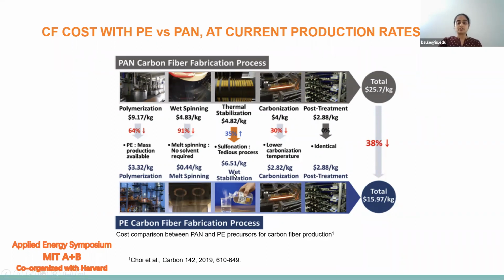Another major difference is that polyethylene is a thermoplastic, so it has a lower melting point of around 140 degrees C. Therefore, it requires some pre-treatment, that is thermochemical stabilization using a sulfuric acid bath prior to the carbonization process. This actually increases the processing cost at this stage compared to the thermal stabilization for PAN precursor.